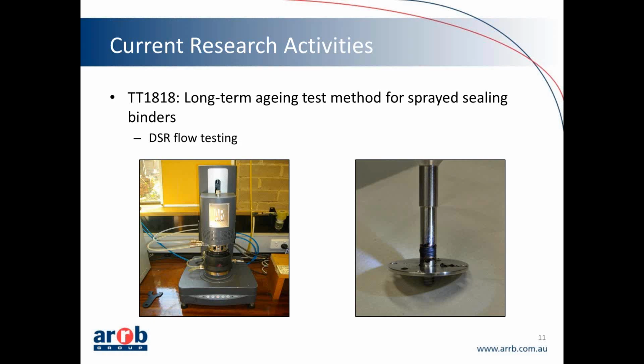And so the summary out of this was we used an ASTM method as the basis for the DSR test method. We have developed a new DSR test method that is currently going through the Austroads approval process at the moment, that will be specific for Australia and is based around quite a sound amount of experimentation here at the lab.